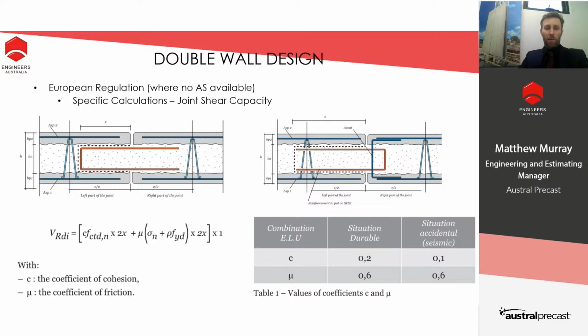On the right-hand side here, we have what we call our stitch connection, which essentially uses a U-bar cast into the panel on the right with the hairpin on the left. What we are doing here is providing a full tension lap for the hairpin on the left-hand side, which enables us to have a full tension lap and go past the girder. The panel on the left is installed first, the hairpins are installed, then the panel on the right, before this hairpin is pulled across and a vertical bar dropped to tie it in place.